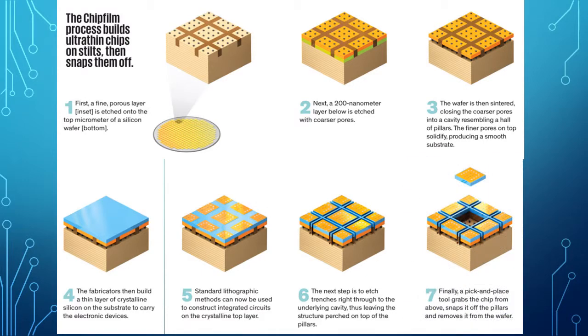Finally, the most important step. A pick-and-place tool grabs the chip from above, snaps it off the pillars, and removes it from the wafer, and we have for ourselves an ultra-thin flexible silicon chip. The chip film wafers are roughly 20 micrometers thick, which is sufficiently thick for leaving them unsupported, yet thin enough to be able to expose them to bending tests.